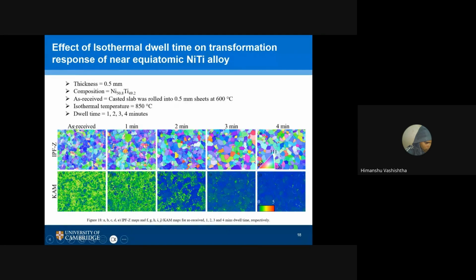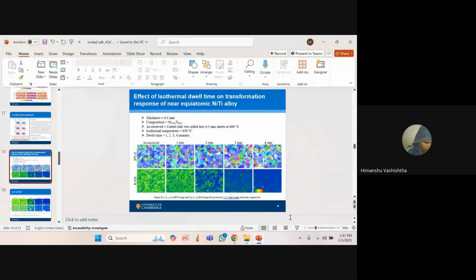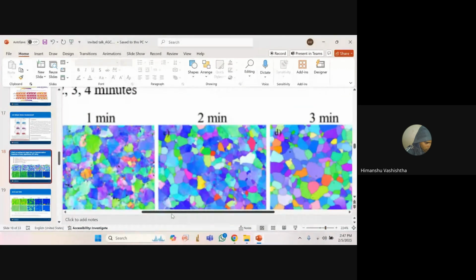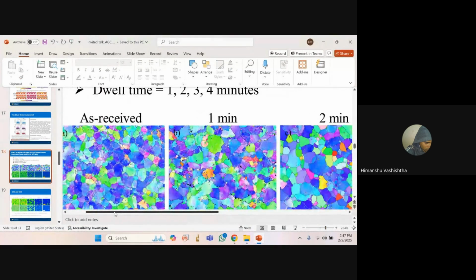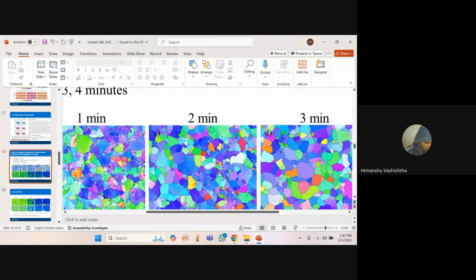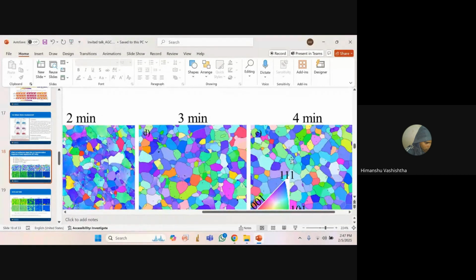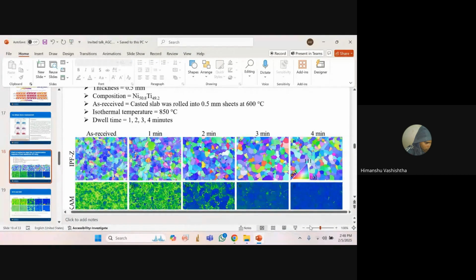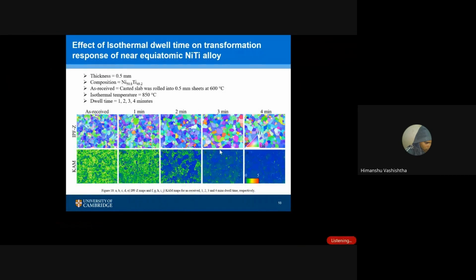So you can see it - if you look here, a few white lines are there. If I zoom it, you'll be able to see a lot of white patches, and these white patches are getting diminished with the increase in heating time, right? A few are retained at 1 minute, then at 3 minutes, and then at 4 minutes it has been almost eliminated, right? Why did I zoom it?